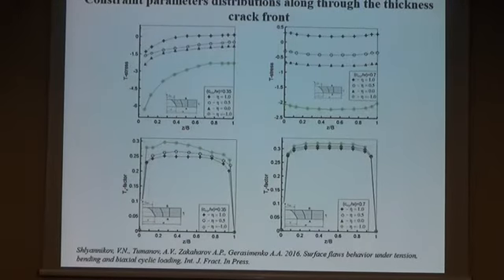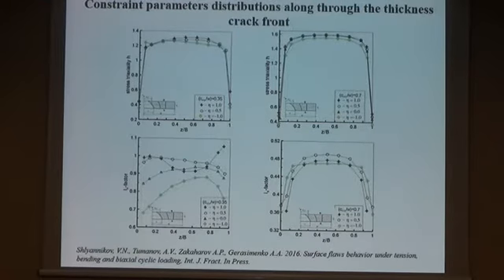In case of through thickness crack, constraint parameters are also presented for two crack front positions that are determined by equivalent crack length 0.35 and 0.7. So we can see distributions of T-stress and TZ factor. And then in this figure you can see the distributions of stress triaxiality and IN factor. And in comparison with surface cracks, parameters T-stress, TZ factor, and stress triaxiality have a more uniform character.